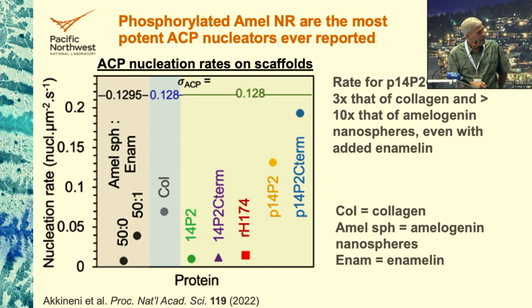This is amelogenin nanospheres with enamelin added in at a ratio of 50 amelogenin to 1 enamelin, which gives you the highest nucleation rate. This is collagen. And you can see that if you look at the non-phosphorylated versions of our proteins, our peptides, they're better than the amelogenin nanospheres, but not as good as with the addition of enamelin or collagen. But when you look at the phosphorylated ones, they're much stronger nucleators. So that's conclusion number 1.